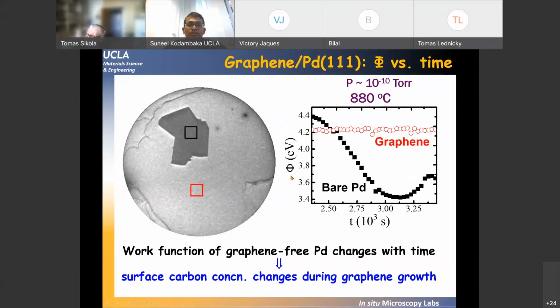By using the electron reflectivity measurements, we can get the work function within this area, and that's plotted as a function of time. For reference, this is the monolayer graphene, and this is the work function of monolayer graphene as a function of time. On the graphene-covered area, there is no change in work function. But in the area that is not yet covered with graphene, there is a significant change in work function.